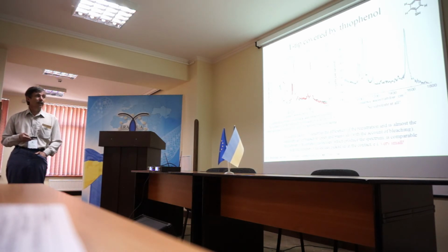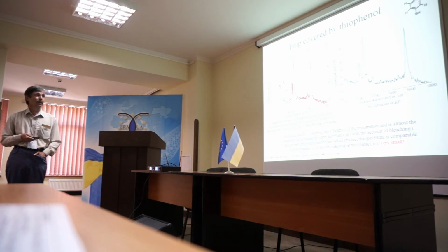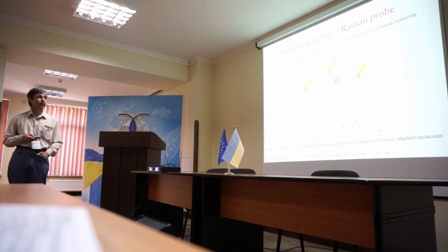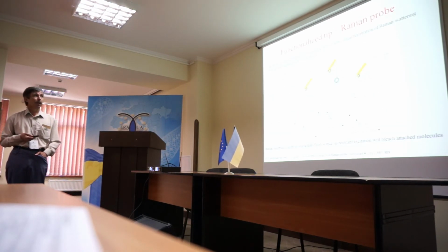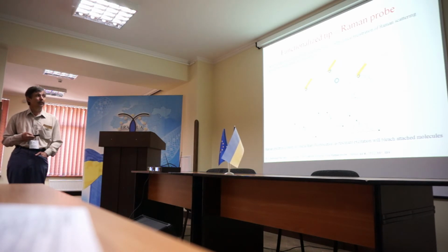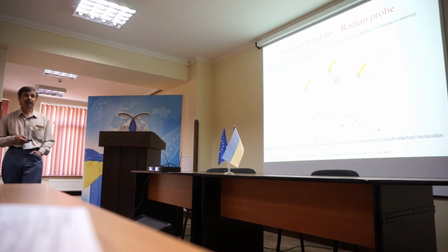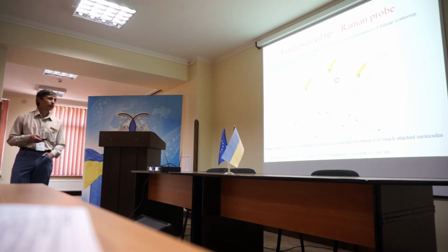Maybe we were lucky, because later it was realized that the tetrahedral tip has its own modes and it has enough enhancement to give us the result. But in fact, what we proposed later is not dependent just on the tetrahedral tip. It's the concept of the Raman probe. So we can cover our tip with Raman active molecules, and if we follow the Raman spectrum just from these molecules, we can make conclusions about the local environment of our apex. So we can expect that spectra would change when we scan our sample.